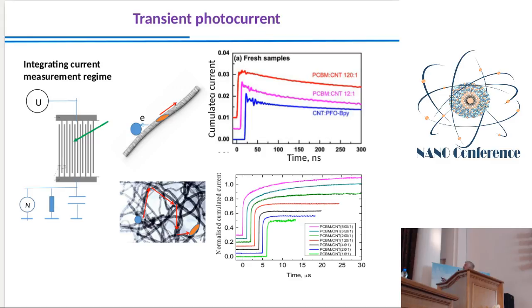At longer times, we also observe some current, so it's derivated, as I told, it's just a current, and this current is due to the electron transfer through the PCBM system. So here we have separation: the hole remains on our carbon nanotube, and the electron goes to the fullerene derivative, and so the electron can also pass through our sample, but only in the case when we have a high fullerene concentration.